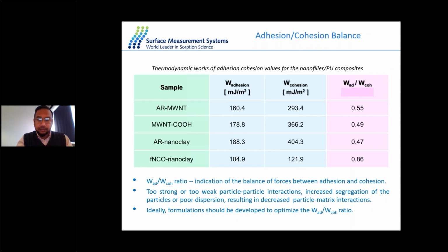Yes, because what effectively you're doing is understanding the work of adhesion and cohesion ratio. What this means is that you're understanding how likely the material is to interact with itself. And if that's very strong, you're going to end up with aggregates. And if you end up with aggregates, you're resulting in very poor blending and poor dispersion in your matrix. However, if you have a lower work of cohesion, then you may get a better dispersion. So it's a really interesting experiment because we can carry out experiments to optimize this work of adhesion to cohesion ratio, to develop a better formulation of your material and obtain a better dispersion of your particle in the matrix. Okay, thank you.